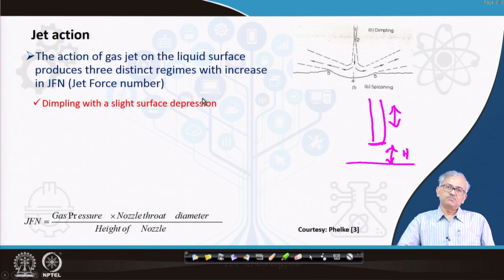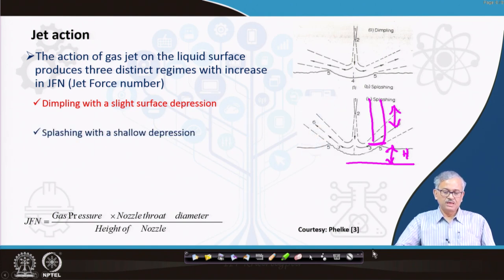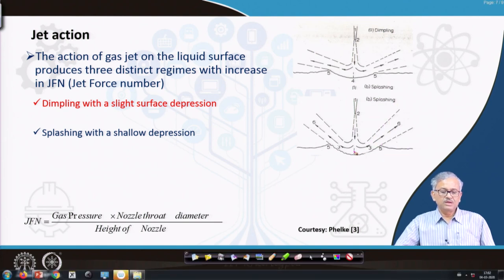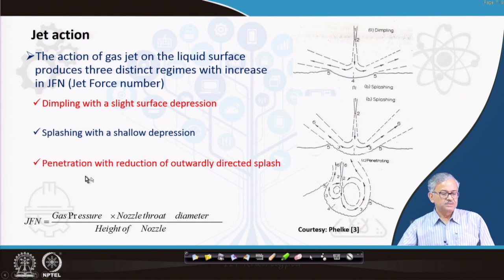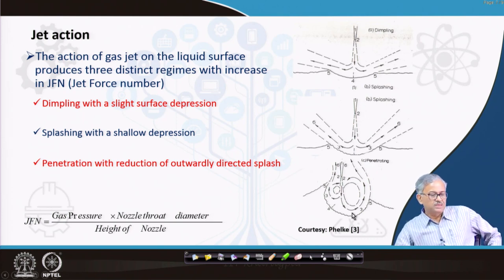Then if you increase the jet force number a little bit, you get what is called splashing with shallow depression. It was dimpling, now it is splashing with shallow depression. Here it was a slight surface depression, here the depression is more compared to dimpling. And finally, if you further increase the JFN, you get penetration with reduction of outwardly directed splash. Now you can find these three: dimpling, splashing and penetration.